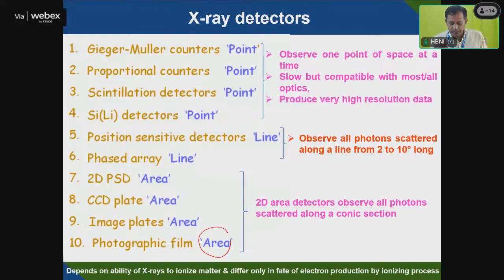The 2D area detector mainly observes photons scattered along conic sections. A point detector observes one point of space at a time. It's a slow process, but a line detector observes all points scattered along the line, from 2 to 10 degrees long. Accordingly you have to select, depending upon the ability of the X-ray to ionize matter, different detectors: the GM counter detector used earlier, then the proportional counter, and the scintillator detector, using sodium iodide thallium, and then silicon lithium, that semiconductor detector. So there are different types of detectors you can use.